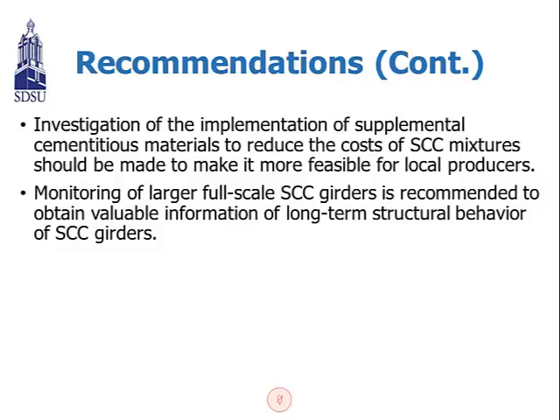And here are the continued recommendations. Investigation of the implementation of supplementary cementitious materials to reduce the cost is recommended, as the mixture should be made more feasible for local producers. As you know, we didn't use any other cementitious material. We didn't use fly ash or anything else. We just chose 800 pounds per cubic yard for the cement. So we recommend using other cementitious materials, rather than only using cement. And the last recommendation was that monitoring of larger full-scale girders is recommended to obtain valuable information on the long-term structural behavior of SCC girders.